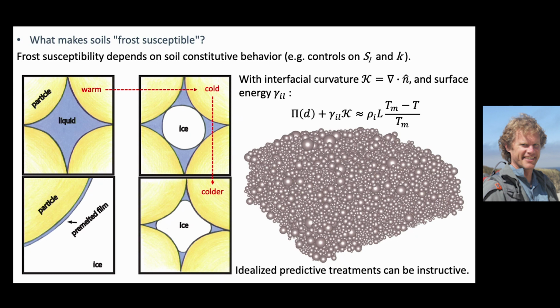We've got a single pore here. It's very idealized. These are the particles. And if it's warm enough, there's going to be nothing but liquid. As we make it cold, the first ice that forms and is stable is going to be a spherical little blob of ice that just fits within that pore. And its temperature is going to be controlled by the Gibbs-Thompson effect that Gray mentioned earlier.